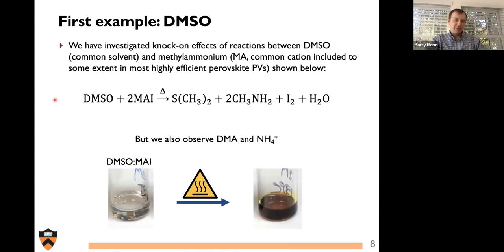So from a very simple perspective, if you add MAI to DMSO and heat it, you can expect a redox reaction to ensue. In this case, whereby something like dimethyl sulfide, methylamine, iodine, and water are created as a result. However, if we take just a solution of DMSO and MAI and heat it, we know that iodine was created by the fact that this solution becomes very dark. But if we do NMR, we also observe formation of other cations, specifically dimethylammonium and ammonium. And these cations can be incorporated inside a perovskite film.